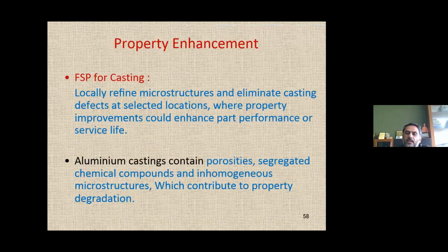So as I mentioned, FSP is also being used for casting. In the casting, you have a lot of porosities. Those porosities also can be handled. You have those porosities at selective locations. So if you want to remove those porosities, you can use the FSP tool to remove them and the performance can be enhanced. So aluminum casting contains porosities, segregations, chemical compounds, inhomogeneous microstructures, which can contribute to property degradation. So the FSP tool can be used even for castings.